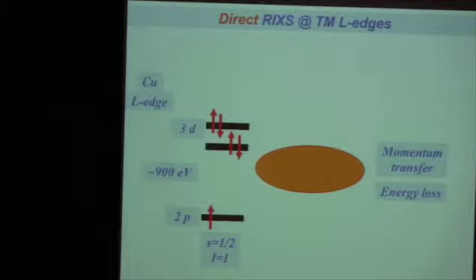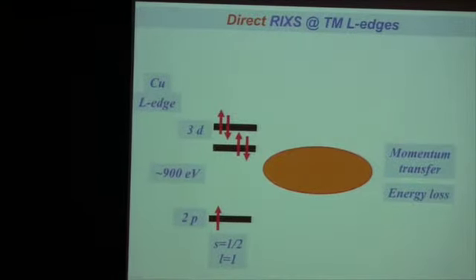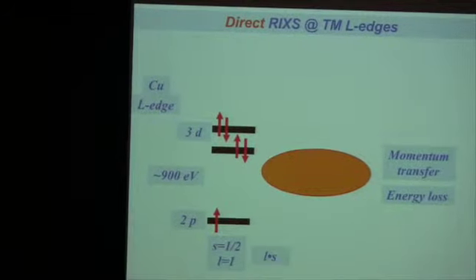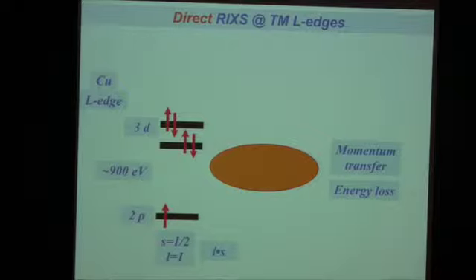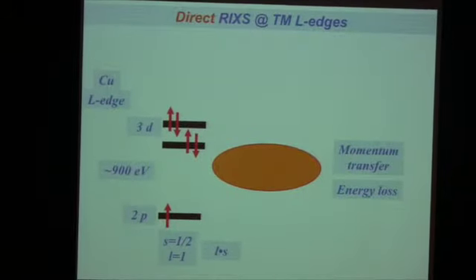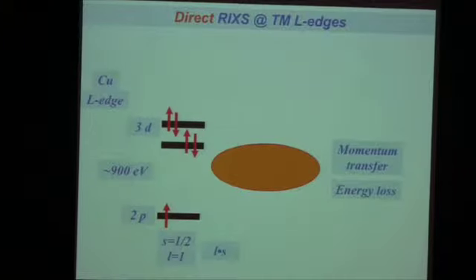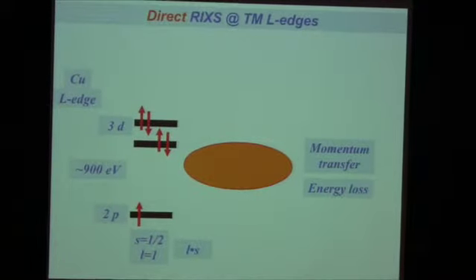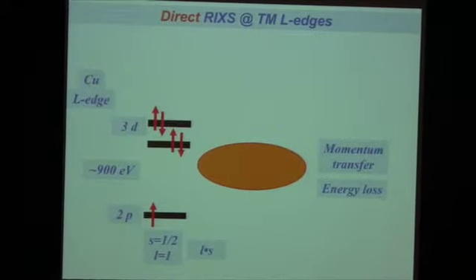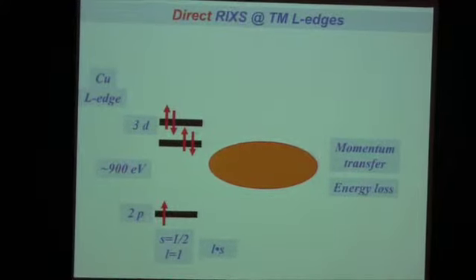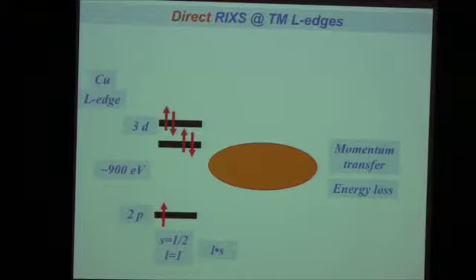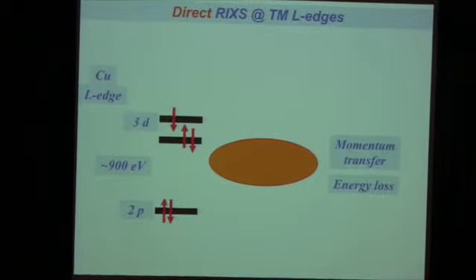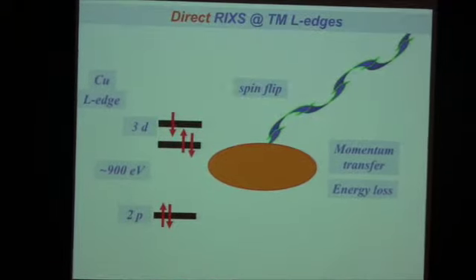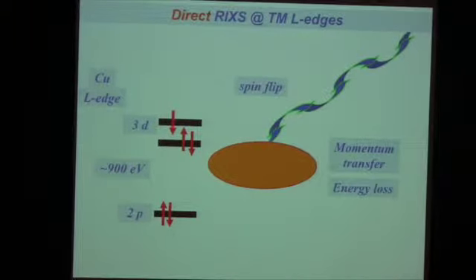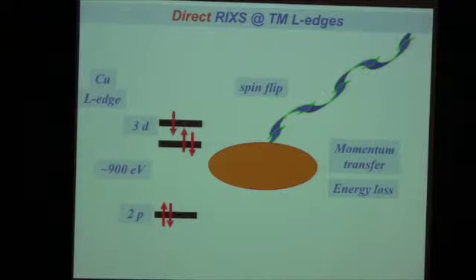It's order 1. It's leading order. Meaning that spin is not a good quantum number, L is not a good quantum number, because L dot S is so large. J is a good quantum number, or loosely speaking, a spin half continuously exchanges its spin angular momentum for its orbital angular momentum. So the spin half is as much up as it is down, roughly. If the spin sitting here is as much up as it is down, then when it is down, an up electron can decay out of this D shell. And what I've done is a spin flip. I've effectively flipped the spin of this 3D electron sitting there at the valence band.